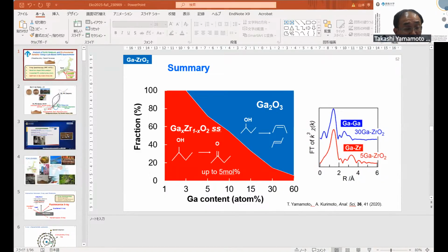A small amount of gallium ion is incorporated into the zirconia bulk, forming a solid solution. This atomically dispersed gallium ion is quite active for dehydrogenation to make the ketone. But when this concentration is up to 5 mol%, the aggregated species is active for dehydration and behaves as a solid acid catalyst like this.